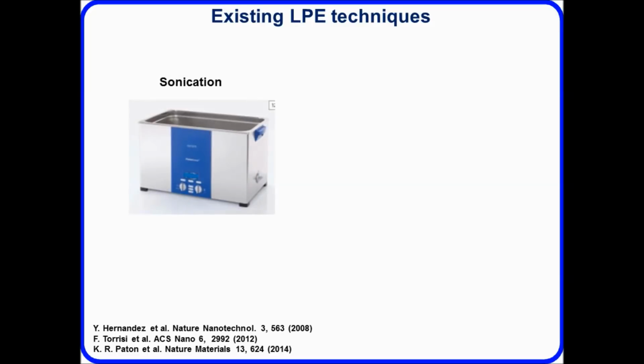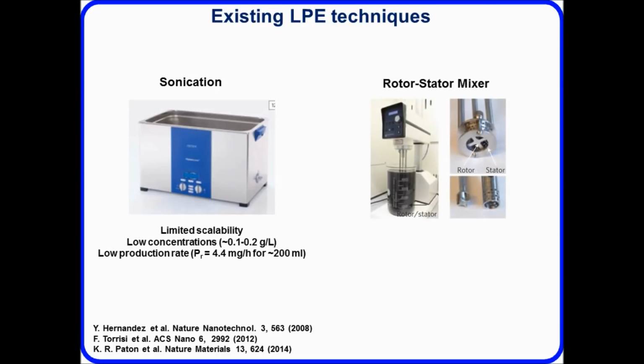Every lab that's producing graphene will have a sonication bath. This process uses ultrasound, which generates cavitation bubbles, and when they implode, they generate high shear forces in the solution. So it's quite a localized process. If you want to scale it, you need to use a much bigger bath, but there are issues with uniformity of the production. You can take this one step further and use a shear mixer. This is much more scalable, and you can produce larger batches. But here you have a rotor and stator, which produces very localized high shear. However, the yields of both of these processes are around 1%, so that's why we looked at exploring other techniques.